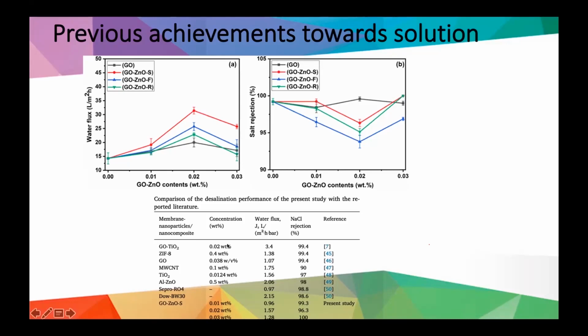Also, as we compare with the published literature and the salt rejection found, in our study, by increasing the percentage of zinc oxide nanospheres and graphene oxide to 0.03% by weight, we find a great enhancement of salt rejection, reaching about 100%. That means all the salts in the water were rejected and the water came out free of salts. This is compared, for example, with embedding graphene oxide alone, which does not give a high rejection; it was recorded in the literature as 99.4.